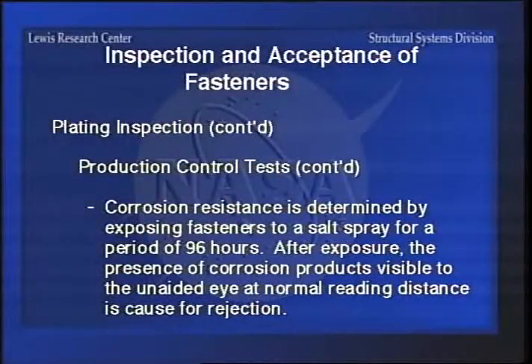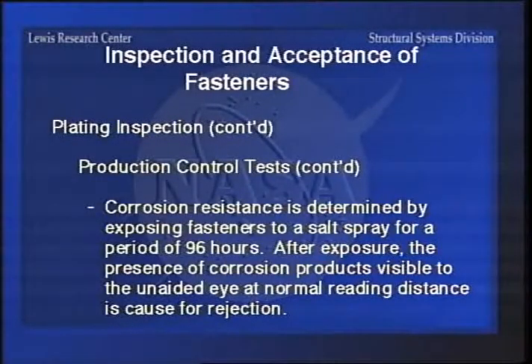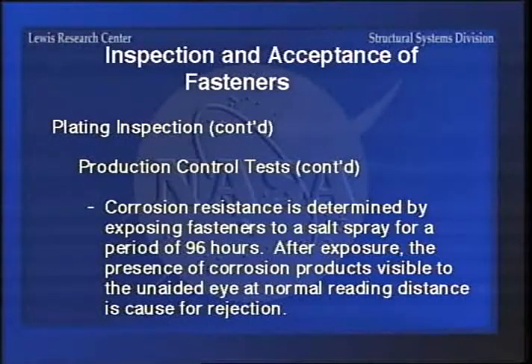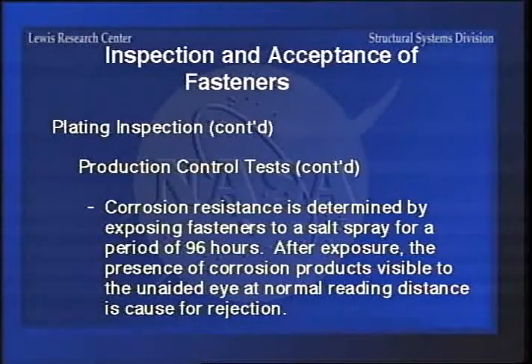Corrosion resistance is determined by doing your salt spray test, which runs 96 hours. After the exposure, the presence of corrosion products visible to the unaided eye at normal reading distance is cause for rejection, because you should not get any rusting or deposition of corrosion products for the 96 hours.